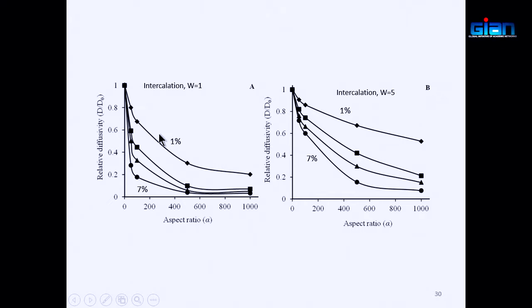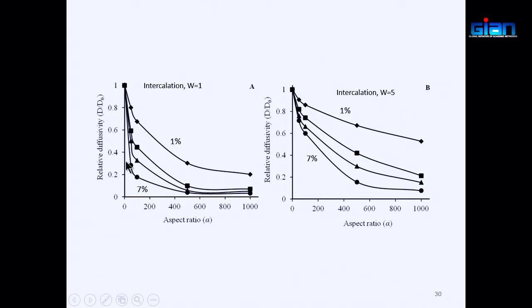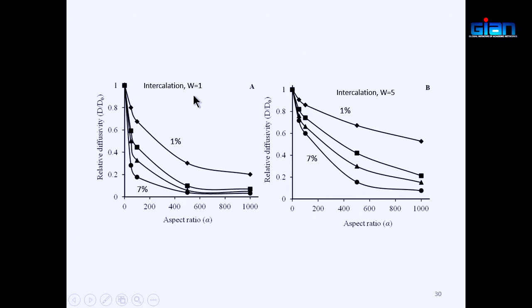This is 1% loading and that is 7% loading. At 1% it is not very effective, and you can see significant improvement from 1 to 3%, some improvement from 3 to 5%, and a little improvement from 5 to 7%. So you can identify where to cut off — for example, 5% gives you a certain level and 7% gives you a bit more. The difference between those two levels corresponds to loadings of 5 and 7.